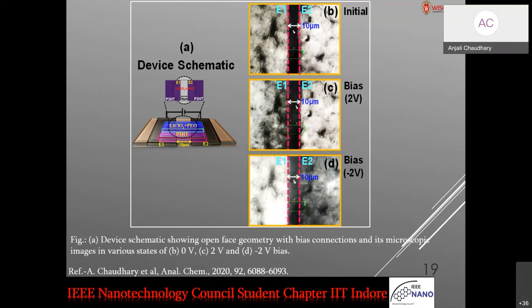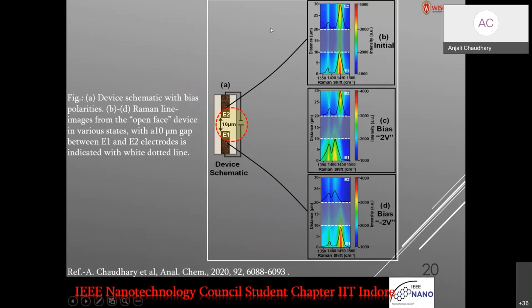So initially at 0 volt, there is no color contrast here. When we apply 2 volt, there is some color contrast. This electrode goes somewhat dark, and when you apply minus 2 volt, it regains its appearance and the other goes dark. Why is it so? Because when you apply positive bias to P3HT, you are inducing some polarons in it, and these can be mapped using Raman spectroscopy.